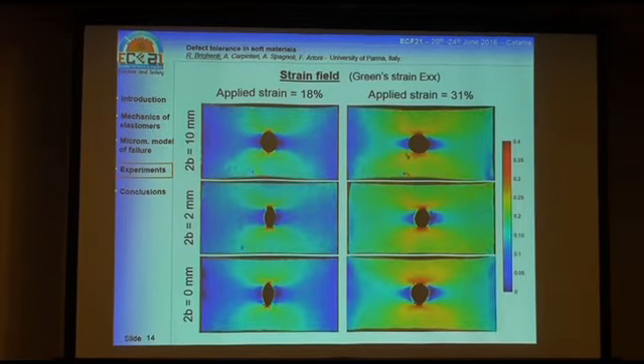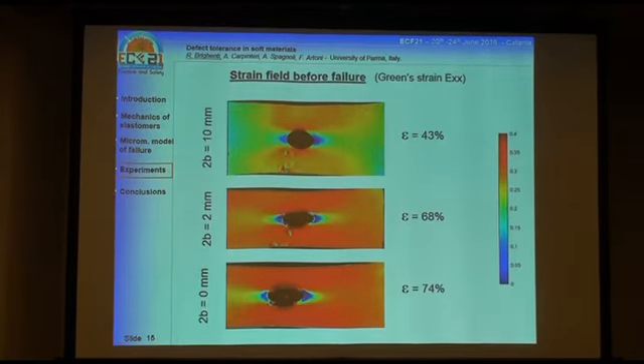These are the DIC images coming from the experiments for the three different kinds of initial defects for an applied strain equal to 18 and 31%. And as you can observe, they are quite similar. So the effect of the initial defect is really low in this class of materials. And just before failure, for example, we are at incipient failure here. You can observe that, for example, in the case of the crack, we can even reach a greater value of the applied strain than in the case of the blunt notch. So, of course, there are some uncertainties in the experiments, but this trend is normally quite common to find in laboratory tests.